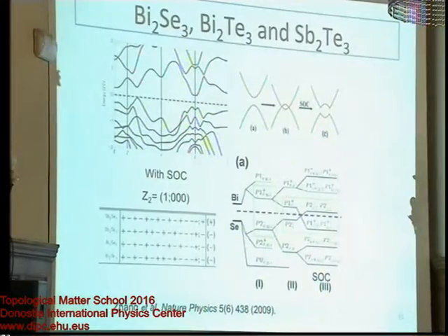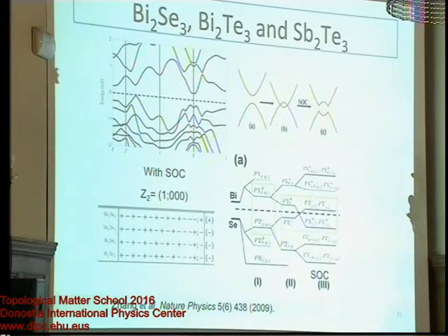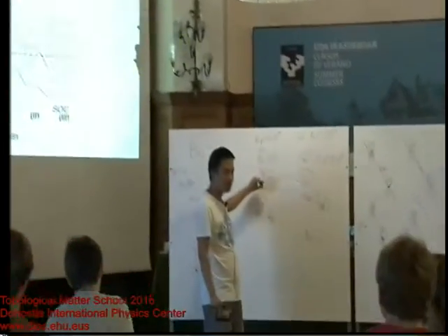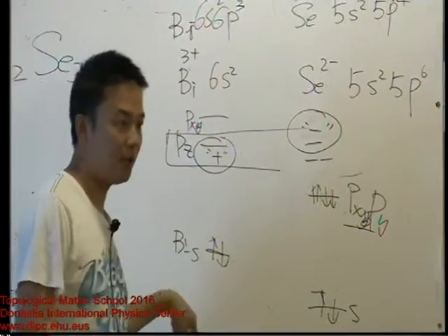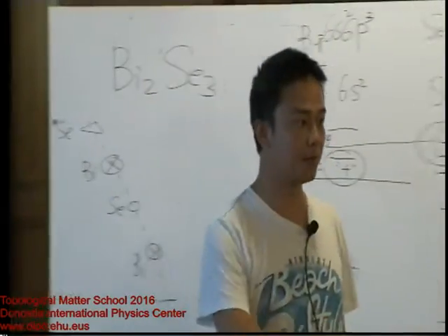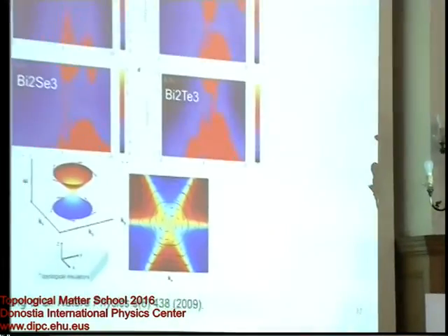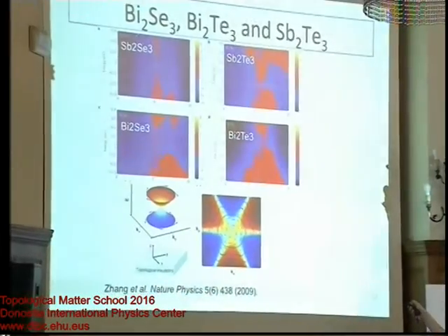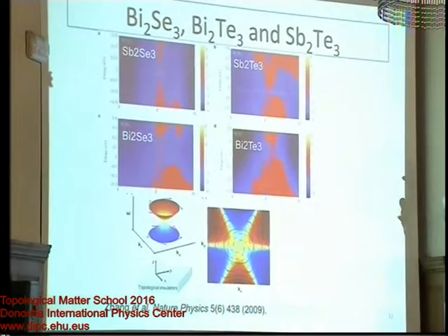And then with this opposite parity, when we turn on the spin-orbit coupling, the spin-orbit coupling simply pulls this down. The spin-orbit coupling simply is this XY split. Larger, split even larger. Then this is pushed up, this is pushed down. And naturally, if the spin-orbit coupling is strong enough, they just get inverted. This is the case for these 3 materials. And unfortunately, for this light one, the spin-orbit coupling is weak. There's some trend, but not enough to invert.